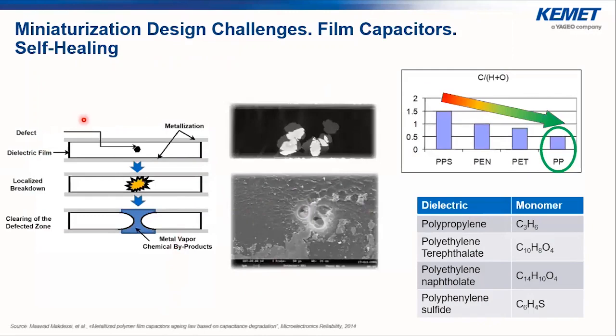First one, the self-healing is a property of metallized film dielectrics, and it is the ability to recover from an internal drop of insulation resistance. This property ensures a safe failure mode in AC frequency applications where electrical noise and peak voltages are added repeatedly or occasionally to the fundamental signal. When the self-healing operates, the temporary breakdown, as you can see here, can occur, which results in a clearing of a small area, causing a minor loss of capacitance and the restoration of the capacitor's initial electrical properties.